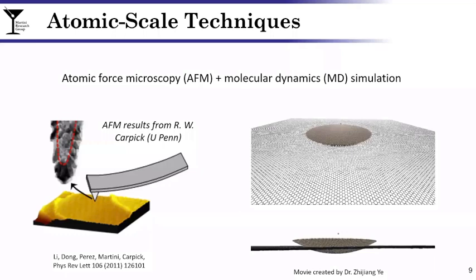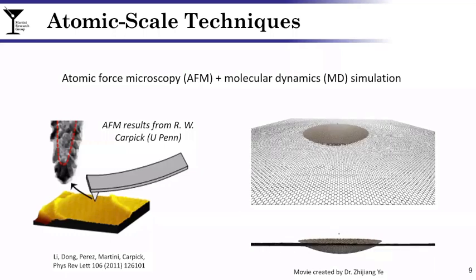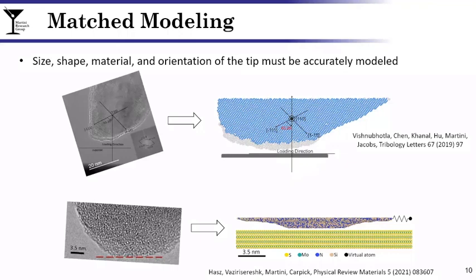I've given many talks where I describe how to create these matched AFM and molecular dynamics models. And here I just want to make one quick point: when we say sliding or friction of MoS2, for example, really what we mean is friction between two things. So any good model must capture both the material of interest, in this case MoS2, as well as the tip. Shown here are just a couple examples where we've taken transmission electron microscopy, TEM, views of the tip to design and model as accurately as possible the apex of the tip in terms of material, crystallographic direction, and so forth. And this is incredibly important for using AFM and MD as research tools together.